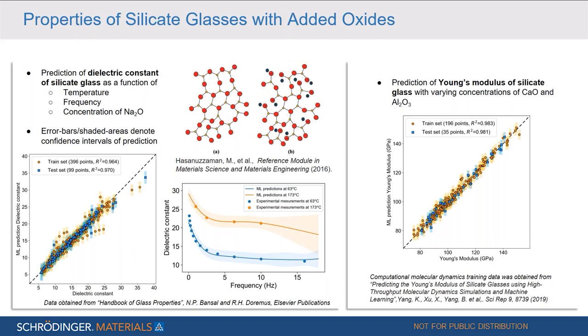We could also use machine learning to look into the Young's modulus of silicate glass with varying concentrations of calcium oxide and aluminum oxide. And here the data were taken from computational molecular dynamics. We see here that we also get a quite good agreement for both training and test sets.